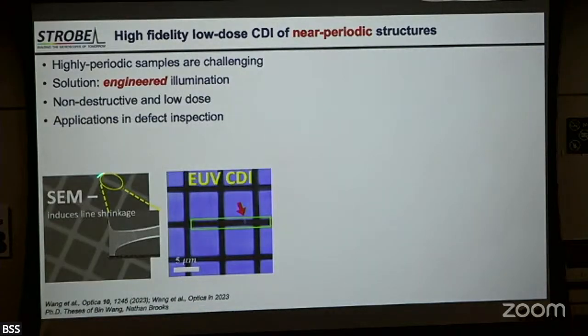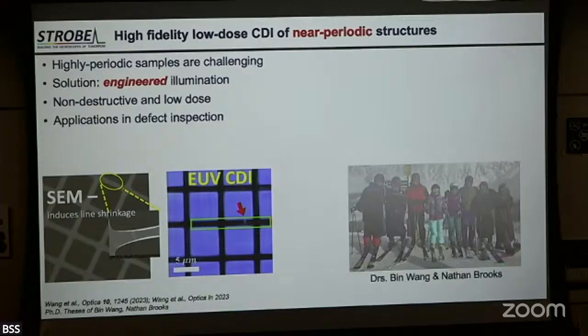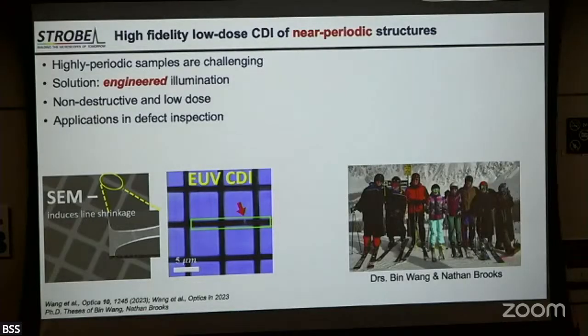Here, it was a perfectly periodic 20 nanometer thin carbon grid. We could see the defect. And when we tried to look at the same little scratch with an SEM, the SEM started to drill out the little 20 nanometer thin grid. And that was part of the PhD thesis of Bin and Nathan.